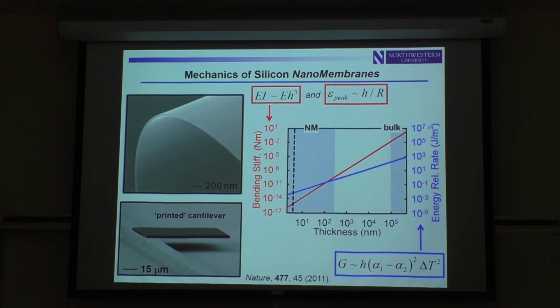But here again, the thickness scaling comes to your rescue because the mechanics are such that the energy release rate parameter G, which defines the propensity for a crack to form between two dissimilar materials, in this case driven by change in temperature and a mismatch in coefficient of thermal expansion, scales down linearly with thickness. So what that means is that as you make the material thinner and thinner, the energy release rate decreases linearly, making it easier and easier from a practical standpoint to manage the adhesion at that interface.